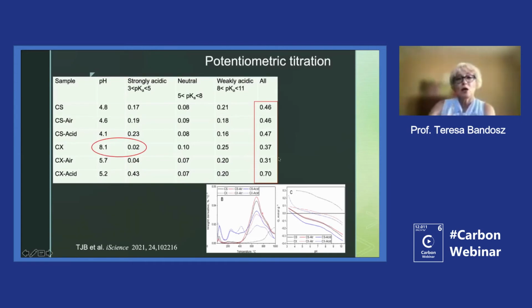And if we look at the differences in all the dissociating groups in our experimental window, they are really not so big. And if we look at the weight loss at the decomposition of the oxygen groups, that CX is very stable, really very stable, and the groups decompose later. So if you look at the peaks for other carbons and carboxyls, you see that, well, there is some discrepancy in this. So that CX was interesting, and that gave us an idea that likely this carbon is very rich in electrons on the surface.